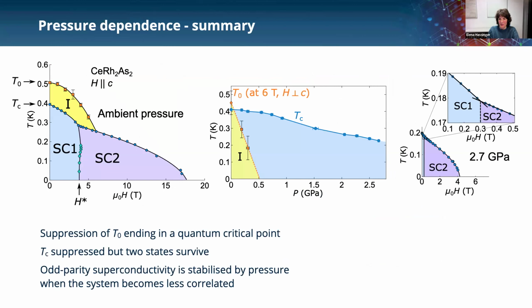Okay, and another important finding is here on the summary slide. If you compare just the superconducting phase diagram in zero field and at the highest pressure, you can see that superconducting state 1, compared to superconducting state 2, strongly shrinks. So it becomes less and less stable with pressure. And so it might be that at some pressure, which we couldn't reach in this measurement, we would get superconducting state 2 even in zero magnetic field, which would be nice. It would be an odd parity state in zero field.